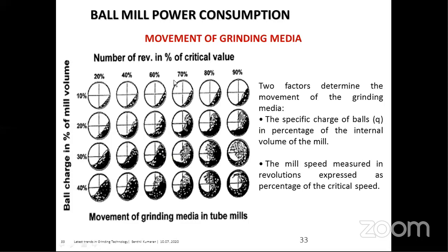Here on the y-axis, the ball charges in percentage of the mill volume: 10%, 20%, 30%, and 40%. And on the x-axis, the movement of grinding media in tube mills at 20%, 40%, 60% of the critical speed, 70%, 80, and 90%. From the top, at a lower filling level of 10% and lower critical speed, the balls won't even lift, so grinding will not happen. At lower filling we are not seeing any impact, so lower filling is also not recommended.